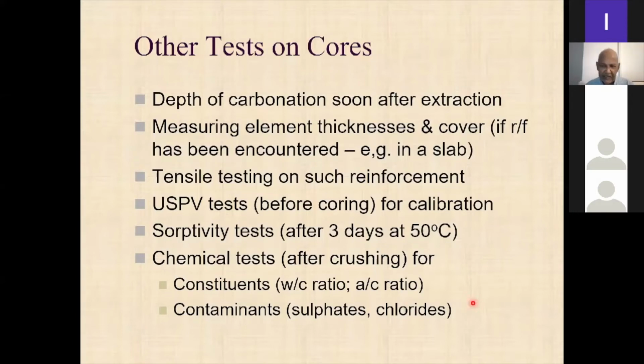You're worried about whether you can do some calculations and see whether this structure, which was normally used as an office building, if it is going to be used as, let us say, a storage area, whether the concrete and the steel properties are sufficient for them, right? And then also you may be worried about durability. So you measure the depth of carbonation, measure the element thickness and the cover, right? If you measure the element thickness, you can get an idea about the actual depth of the concrete, right? You may even, with some judgment, be able to reduce the partial safety factor for dead load, because you have now a very accurate estimate of the element thickness, right? But that requires some expert judgment, right?